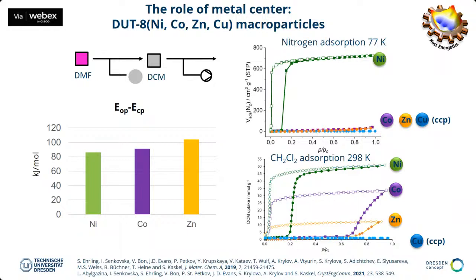And this you see also in the energetics. When you calculate the energy difference between the open pore structure and the contracted pore structure, you see that the energy difference is the smallest for the nickel, but the largest for the zinc. That means for the zinc structure, the closed pore structure is actually the most stable one, compared to the nickel, because the nickel is more a harder spring. It tries to reopen the structure. It pushes the structure open again.